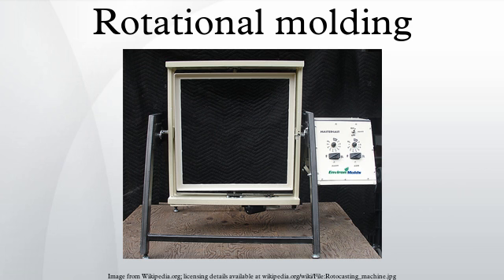When the depth of the recess is greater than the width, there may be problems with even heating and cooling. Additionally, enough room must be left between the parallel walls to allow for the melt flow to properly move throughout the mold. Otherwise, webbing may occur. A desirable parallel wall scenario would have a gap at least 3 times the nominal wall thickness, with 5 times the nominal wall thickness being optimal. Sharp corners for parallel walls must also be considered. With angles of less than 45 degrees, bridging, webbing, and voids may occur.